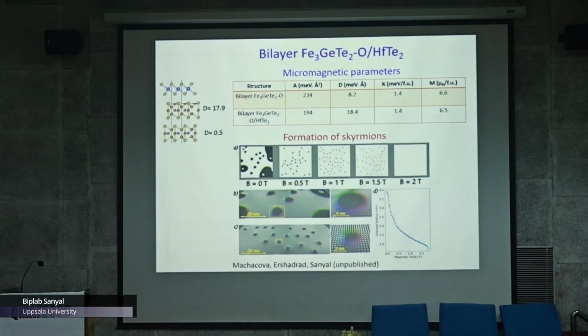And another interesting thing is that you can see the formation of skyrmions even at zero applied magnetic field. And when you apply a magnetic field, then finally at 2 Tesla, that disappears, so you do not see the formation of skyrmions. So anyway, this is a hypothetically designed heterostructure combination where one is able to see the formation of skyrmions because of this sweet combination of all these parameters in your spin Hamiltonian.